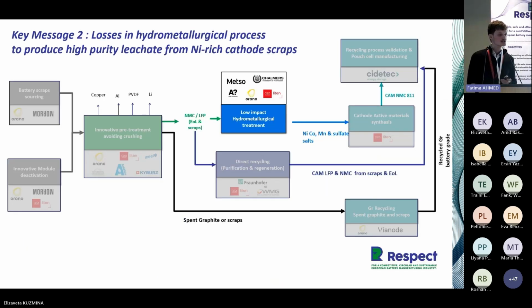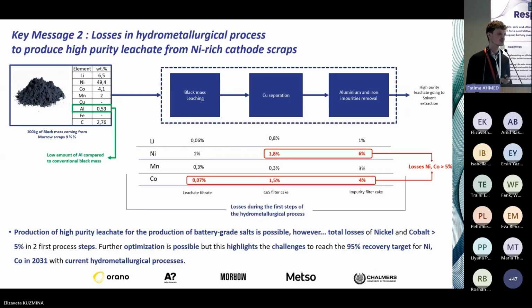Second message of today is related to the next part of the recycling process, so the low impact hydrometallurgical treatment. Here we have demonstrated that we managed to produce high quality leachate that can be used to produce battery grade salts. However, we have observed some significant losses in the pilot test that was conducted, and we need to keep that in mind for the future. Here are the results of the test that has been conducted.